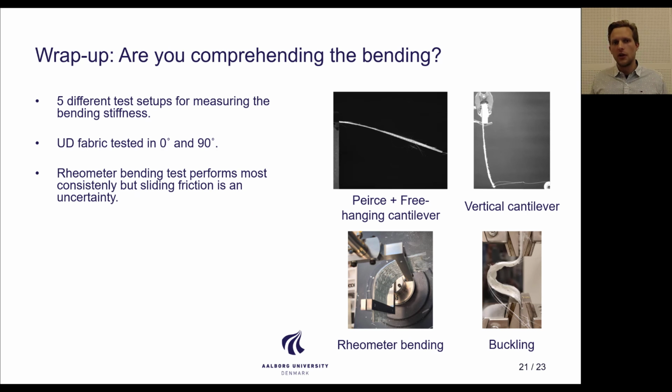So overall you can say that the rheometer bending test performs the most consistently, also within the repetitions of the test, but it suffers from this issue of sliding friction in the clamp, as well as whether the curvature is in fact constant between the clamps.